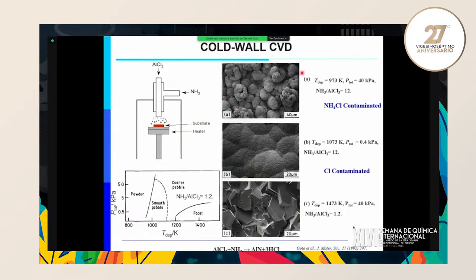So you can see many cauliflower-like aluminum nitride forms at some conditions, and also comb structure aluminum nitride forms at rather low temperature conditions. And sometimes we have to control the distance between the nozzle and substrate. So we need many experiments to make very good aluminum nitride, very faceted films. These are agglomerated particles; the cauliflower-like structure contains impurity ammonium chloride, and the cone structure aluminum nitride contains chlorine. So we have to make this kind of very faceted, very good material.